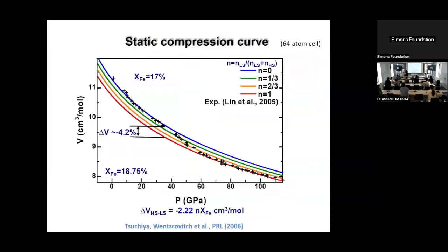This is huge. And this is what we started doing in 2004. The LDA plus U was not even published, as we know today, but I was collaborating with co-author Stefano de Gironcoli. So here is, for example, 18.75% iron. It's 64 atoms per cell, and I have 6 iron ions. This is MgO, right? Six iron ions, and they are as far as possible from each other.